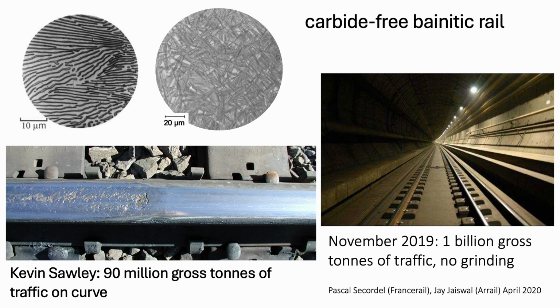Now, most rails have a microstructure which is an intimate mixture of soft ferrite and hard cementite, which is good for wear resistance, but the rolling contact fatigue performance could be better. We invented a completely different rail microstructure containing no carbides at all, just bainitic ferrite and retained austenite, quite a tough combination. And this has a hardness which is no problem and is excellent in rolling contact fatigue resistance.